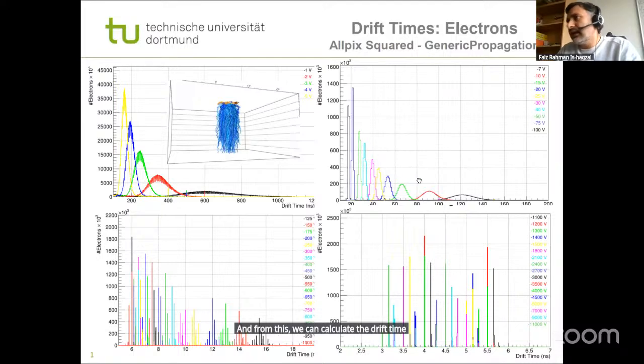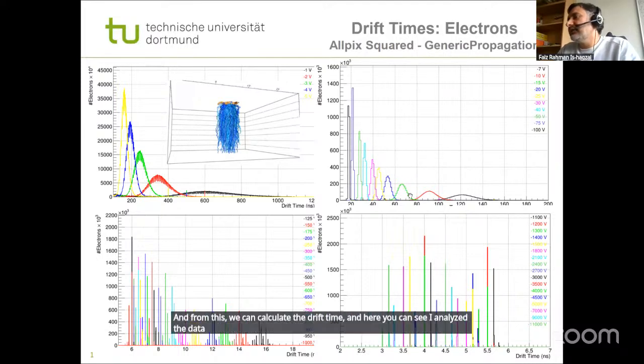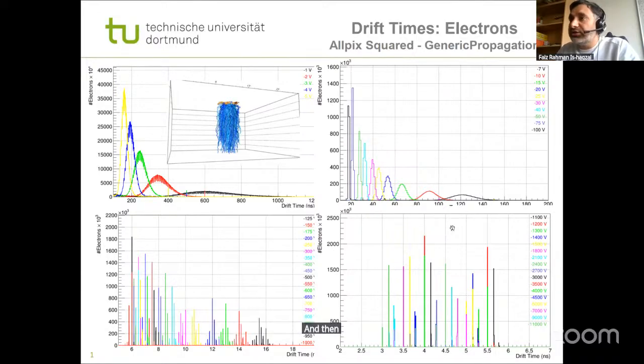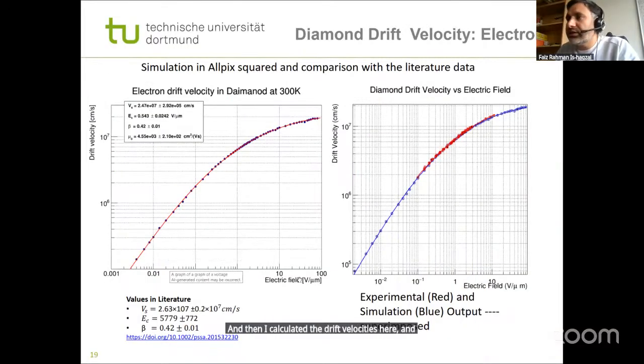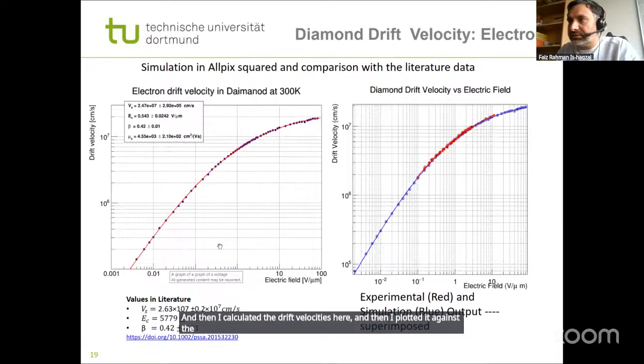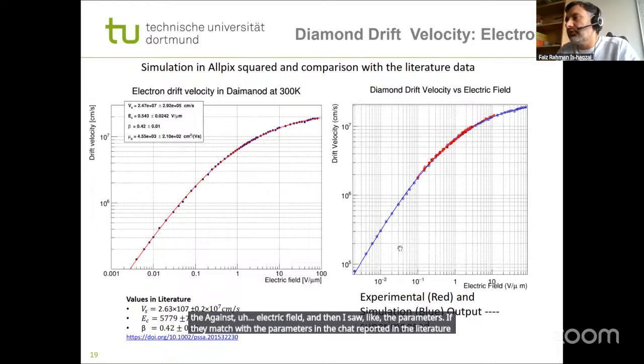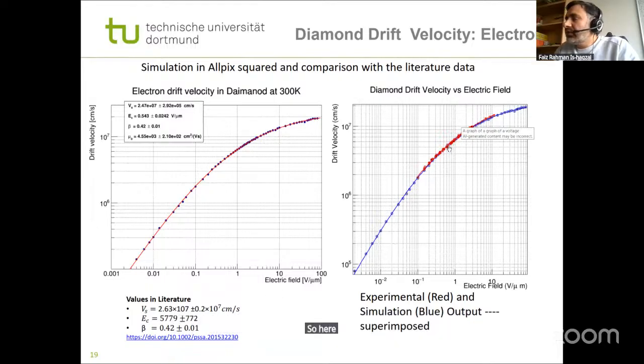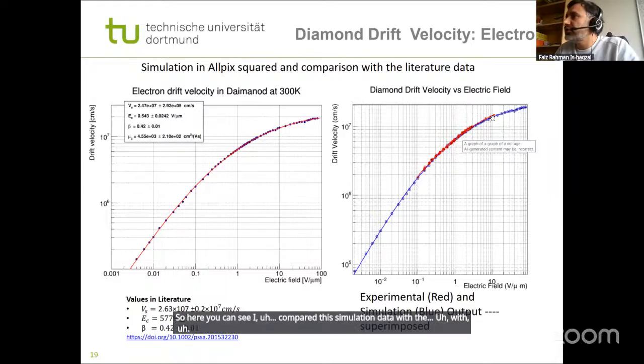Here you can see I analyzed the data. I took the drift times for the different voltages, calculated the drift velocities, and plotted them against the electric field. Then I checked whether the parameters match those reported in the literature data, and they did. I compared this simulation data with the literature data, and it superimposes perfectly.